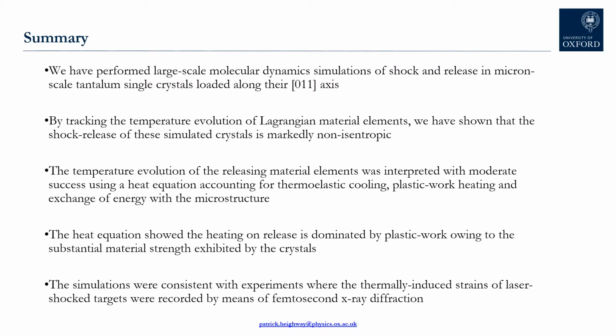So our work can be summarised as follows. We've performed molecular dynamic simulations of micron-scale tantalum monocrystals that are shock compressed to about a megabar and are subsequently allowed to release back to ambient pressure. We've tracked the temperature evolution of a set of Lagrangian material elements that are equispaced along the length of the crystal, and we've found that their release is markedly non-isentropic, which is to say that they are far hotter than expected. We've attempted to interpret their temperature evolution as coming from a sum of thermoelastic cooling due to expansion, heating due to plastic work, and exchanges of energy with the material microstructure with moderate success.